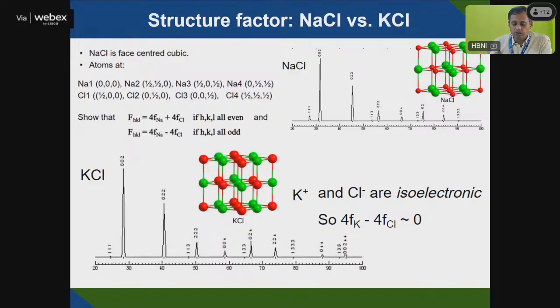So if you see the structure factor as I discussed, NaCl and KCl, in NaCl the 1, 1, 1 peak you can see here, but in KCl, as I told, it is missing. So this 1, 1, 1 is absent here, whereas here you are getting a peak. Here it is absent.